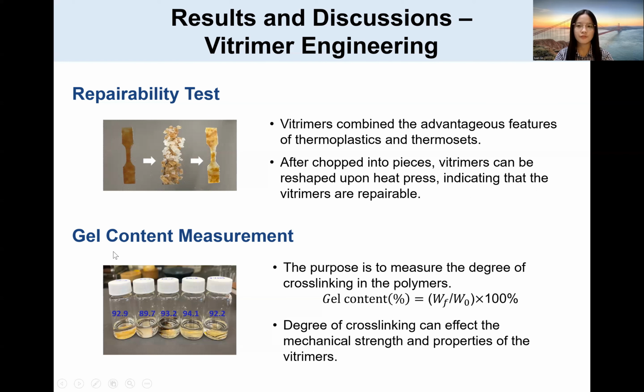And gel content reflects the cross-link density of the vitrimers. So that means if the polymerization step is completed and more successful, the gel content, the cross-link density of the vitrimers, will be higher. And as you can see here, the gel content of the samples are all around or even above 90%, which means the polymerization step is complete, and it can be further used for heat press.